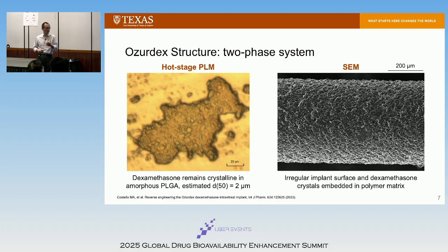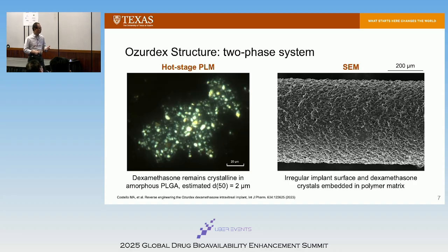You have basically dexamethasone dispersed in the PLGA, with dexamethasone retained as a crystalline. There's very little interaction between dexamethasone and PLGA. Dexamethasone has a high melting point, okay? And we have done studies to understand if there's any solubility at high temperature. There's not. Dexamethasone does not dissolve, it's just simply dispersed in there.